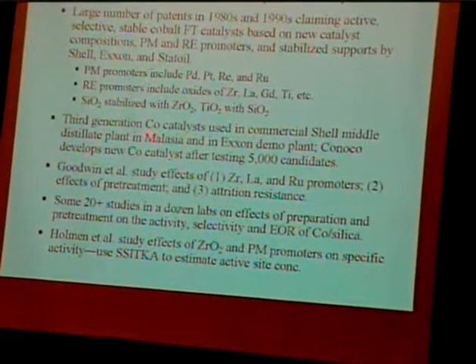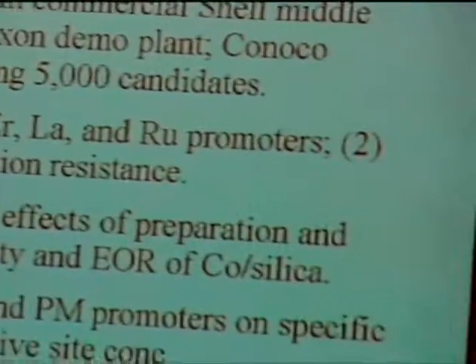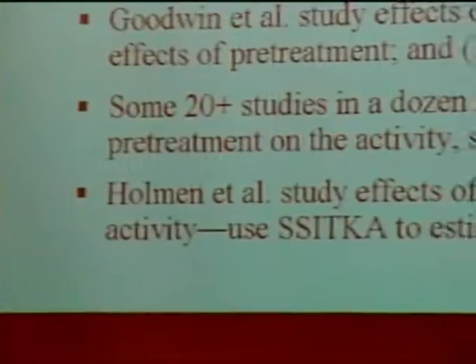We have some more scientific studies. Goodwin et al. studies zirconia, lanthanum, and ruthenium. Some 20+ studies in a dozen different labs on the effects of preparation and pretreatment on the activity, selectivity, and extent of reduction of cobalt silica catalysts.